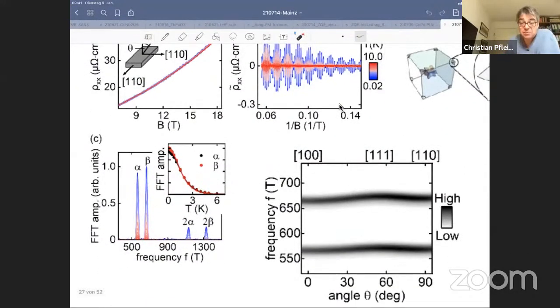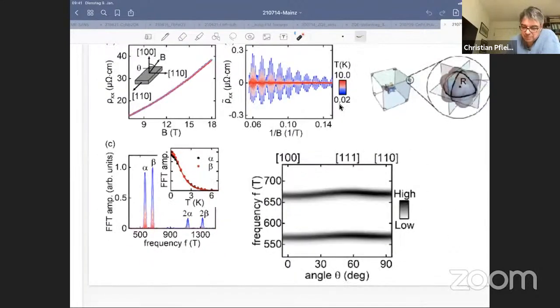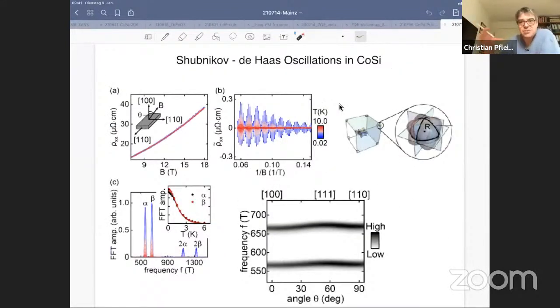And you do a Fourier transform of these oscillations, and we confirmed that what these 3 Chinese papers published was perfectly all right. Actually, just by seeing an oscillation, you don't know exactly which Fermi surface pocket this is. You could, in principle, also have something that originates from the gamma point, but there are some arguments that basically say these two here have to be attributed to the R point. So you see these 2 oscillations, and you think there are 2 Fermi surface pockets, and that's it. Without spin-orbit coupling you have 2 sheets, and with spin-orbit coupling you have 4. So you think, well, 2, perhaps spin-orbit coupling is not very important, right?